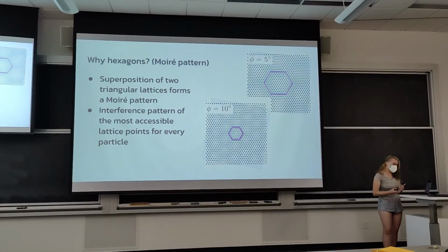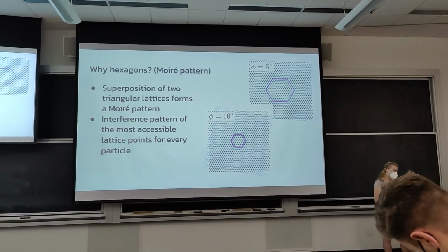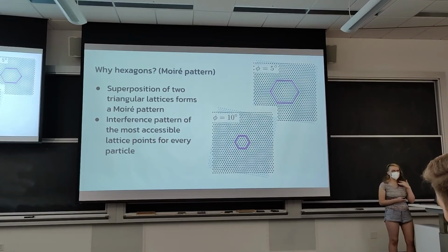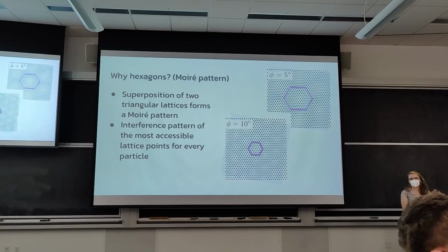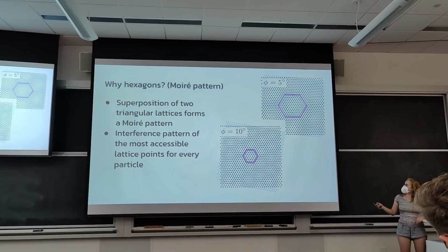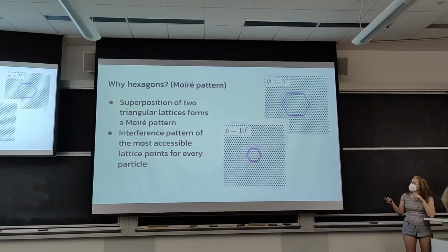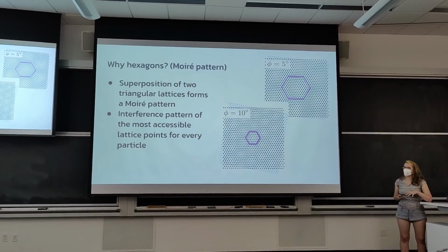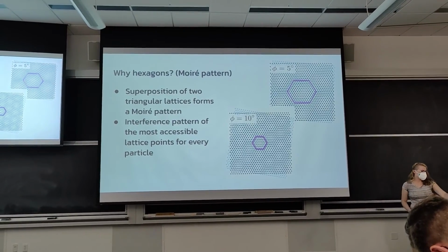Now, we only have one layer of particles at a time, but the action of switching from one grain to the other grain is effectively a two-lattice problem. So imagine extending the outlying lattice into the interior lattice. And so the fastest way for particles to align themselves with the outlying grain is to find the nearest lattice position that corresponds with the outer grain. So in this case, moving from like one grain to another is a simple case of rotating each particle towards the imaginary lattice points placed on top of it from the other lattice. It forms this hexagonal Moiré pattern, and we get granules.